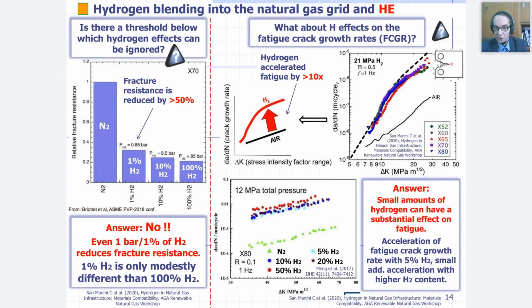The next question is, what about hydrogen effect on the fatigue crack growth rate? Because pipelines are exposed to pressure cycling and also fatigue. The immediate answer is that small amounts of hydrogen can have a substantial effect on fatigue. Acceleration of fatigue crack growth rate is detected with only 5% hydrogen in the mixture, with additional small acceleration with higher content. We can see that in the down middle part of the slide. As you can see, we have the increase in fatigue crack growth rate in comparison to the green dots related to N2, for 5, 10, 20, or even 50%. So the increase of fatigue crack growth rate is very similar for different hydrogen blending ratios.